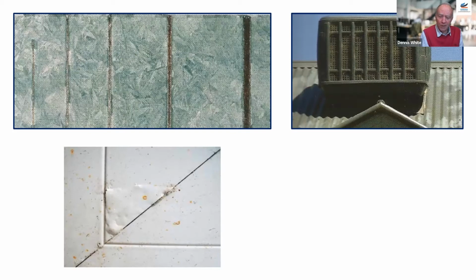When it comes to painted surfaces, they are equally vulnerable. And the bottom left-hand corner shows one of the samples prepared for a salt spray test, where you can see the undercreep, where the cathodic protection is no longer working. It's being consumed, because if you can imagine a cross-section through that, you've got probably 8 to 15 microns of primer on top of your steel substrate, and you've got 19 microns of color on the top if you're lucky. And once you've penetrated through that, the flow across the cut edge, if you could imagine the end of a piece of cladding where the edge is cut, on a painted surface, you've got just a very small surface of zinc to provide the cathodic protection. And once you got past that, then the stuff starts to corrode underneath, and it'll attack the under surface, and you'll get a delamination.